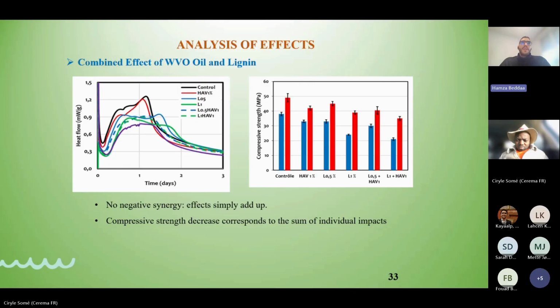The same for the compressive strength, so the results of the compressive strength tell the same story. When we use lignin and oil together, the compressive strength decreases, and this decrease is the sum of the decreases of the two additives when we use them separately and individually. So we can see there is no interaction between oil and lignin, their effects are individual, and there is no synergy between these two additives.